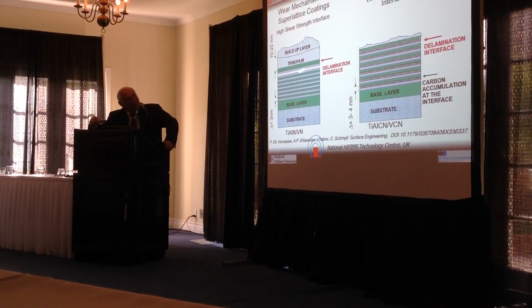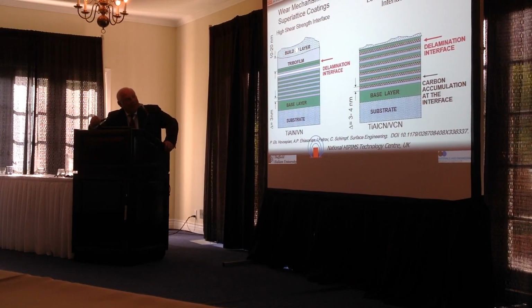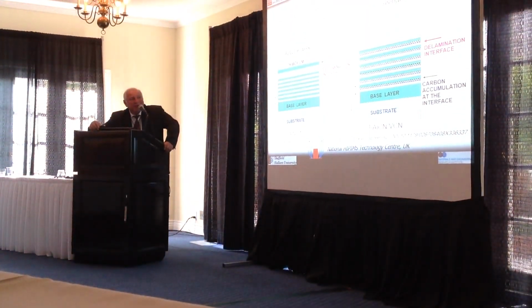And this is just the schematic. That is the carbon-free version, the individual layers. You always form a tribofilm on top. It does react with your aluminum workpiece material, produces a huge build-up layer, then it will shear away this interface here, and a big chunk of coating material will be lost. When carbon is segregated in the interfaces, you are in a layer-by-layer wear mechanism, and this layer-by-layer wear mechanism is on the nanoscale. So with this approach, you don't actually prevent the metallurgical reaction, because you cannot cheat nature. But you can produce a material which has a special topological behavior.